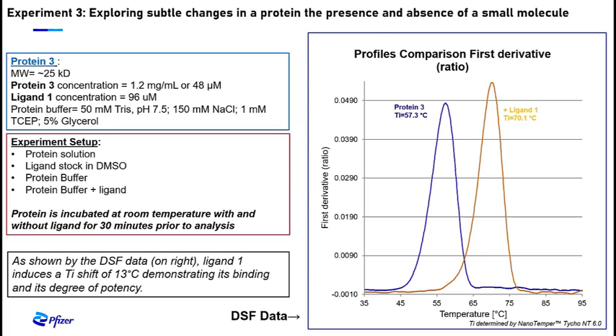Upon sample preparation, the APO and ligand bound protein will be incubated at room temperature for 30 minutes prior to analysis. The DSF data on the right shows that the APO protein has a TI of 57.3 degrees, which is quite stable already without anything bound. After adding the ligand to the protein, we show that it stabilizes quite well with a temperature shift of 13 degrees, which is quite good. We know it's binding.